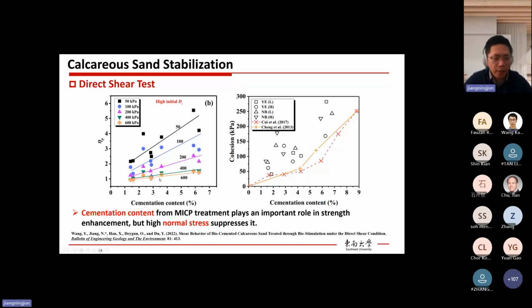But on the high normal stress levels, like 400, 600, the peak stress ratio still increases with cementation content, but only a little bit. So it means that on the high normal stress conditions or high confinement conditions, although MICP could still work, it could not help too much, because at this time the confinement dominates the strength of sandy soil.